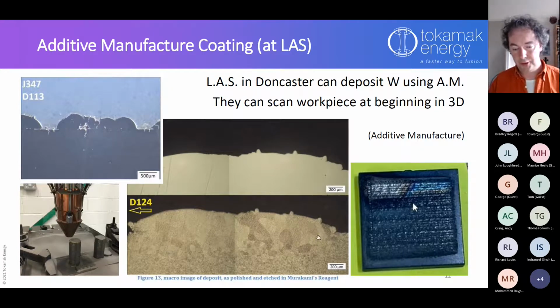This is a cross section, and this blob on the top is the additive material, and underneath is the substrate. We're putting it on, and you'll see it's bonded. The crystalline structure bonding looks good. The crystals are bigger here. This is the crystal size on the base plate, if you like, but there isn't significant cracking. It's looking pretty good, and that's the kind of thing that the samples look like.